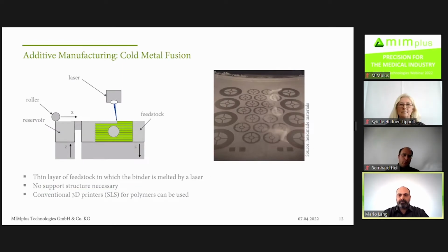So, more to explain the additive manufacturing, one technology we have in-house is the so-called cold metal fusion process. So what's that like? You have a powder, a bed of powder. This powder is the metal powder, which is surrounded by a thin layer of plastic. And you use a laser with conventional 3D laser printers. And you melt off the plastic, and by melting off the plastic, you have a fixture between the different metal powders. And so you can form a thin layer of your part. After that, you have a roller and you add the next layer of feedstock, you laser them, and in this way you build up your part layer by layer.